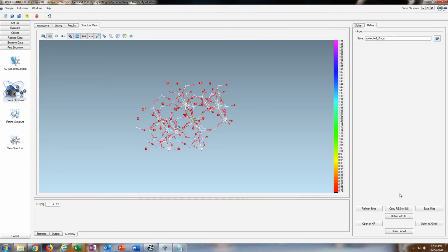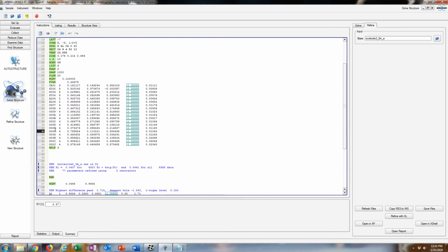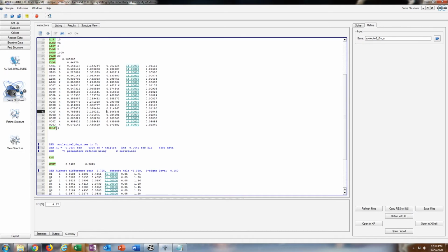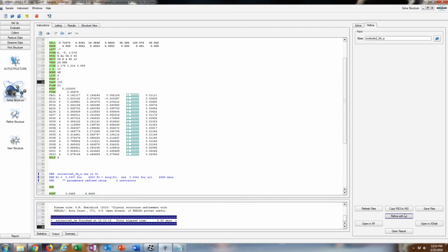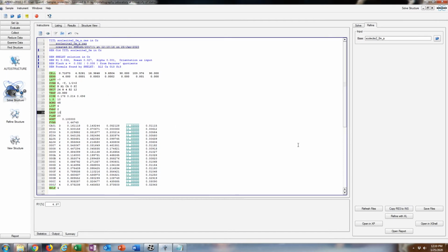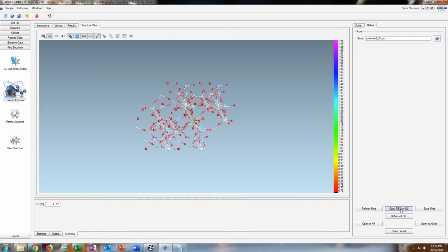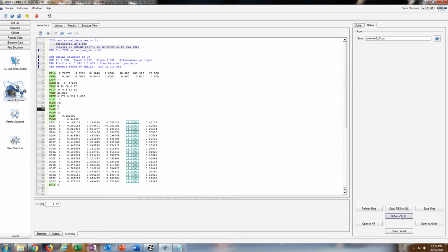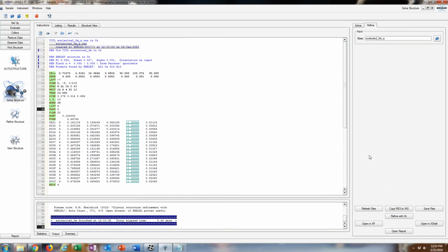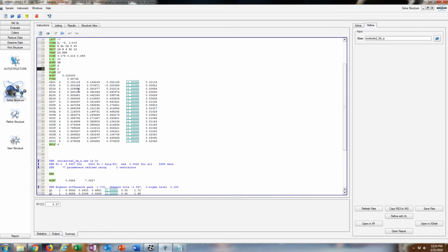Alright, that looks good. I dampened the structure. Damp 1000 is the command, just in case it blows up. That will control it a little bit. And this actually worked immediately because it's in the correct convention, or it was the correct lattice after all. So those are the fractional coordinates you want to use. And I will take away the damp command. Yeah, it's just a way of controlling how aggressive the refinement goes.